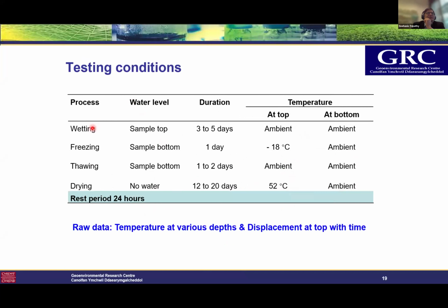These are the testing conditions. What exactly was the water table position, and what was the temperature at the top and bottom of the sample is shown there. During wetting, the water level was at the sample top. It took about 3 to 5 days, and the temperature was ambient. During the freezing condition, the water level was at the bottom of the sample. So the sample had access to water, and the freezing cycle continued for only 1 day, 24 hours. And the top of the sample had a temperature of minus 18 degrees centigrade, and at the bottom, the temperature was about 20 degrees centigrade.